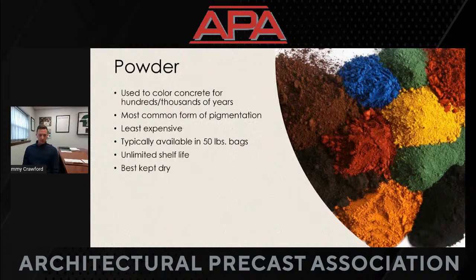Powder is generally available in 50-pound bags. There are some that are slightly more, slightly less as the standard size. It can obviously be rebagged into any size. Has unlimited shelf life. There's no spoilage, it doesn't lose its tinting strength over time or anything like that. It's best kept dry, and basically that's just to avoid clumping issues. So if it gets wet, it might ball up.